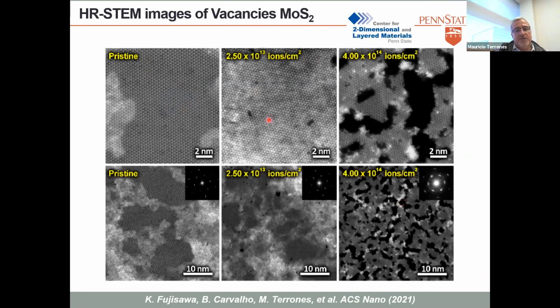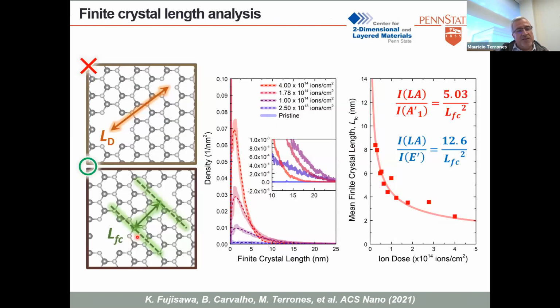This is after ion bombardment. You can see lower mag or higher magnification. You can see how bad the sample can be, right? So basically, you irradiate and you remove lots of material. But what can you measure? So one thing we did is the finite crystal length, which is this distance.